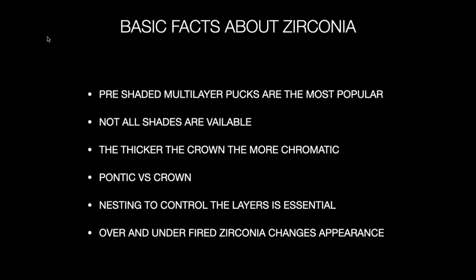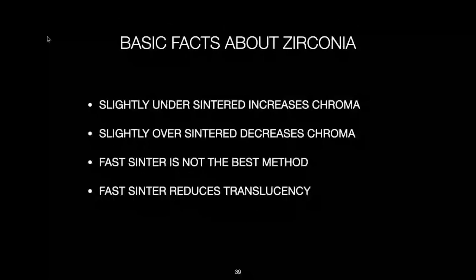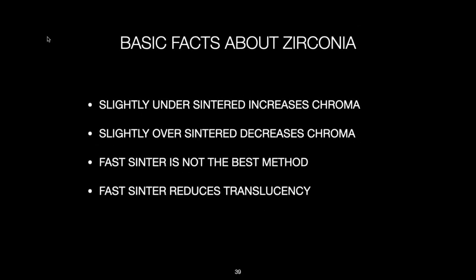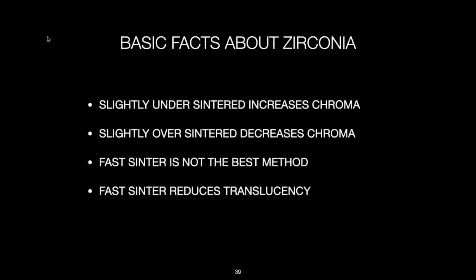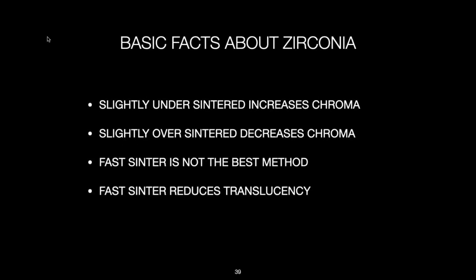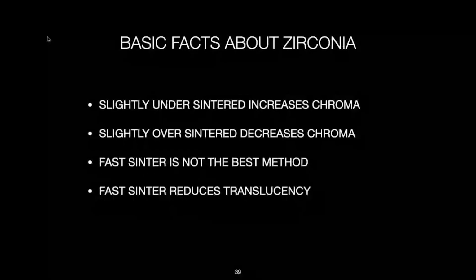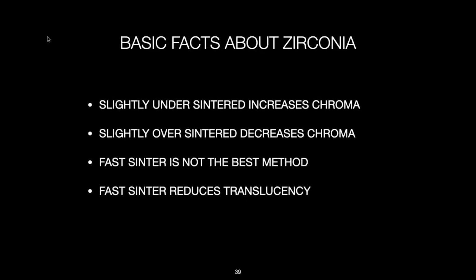So slightly under sintered zirconia increases the chroma. Slightly over sintered decreases the chroma. Fast sintering is not the best method, and fast sintering reduces translucency. I know they're working on all kinds of zirconia, and they'll say, yeah, you can cook this thing in an hour. It's like name that tune. I can cook that crown in 3 bakes. I can cook it in 2 bakes. Oh, bake that crown. It's incredible.